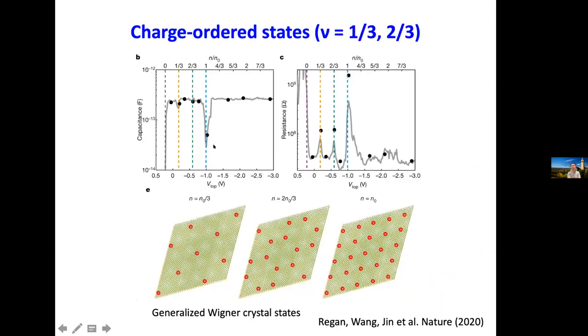Feng Wang's group used an optic technique to probe the charging dynamics into the Moire superlattice. In the resistance channel, they were able to identify peaks at 1/3 and 2/3, and they assigned those two states to generalized Wigner crystal states.